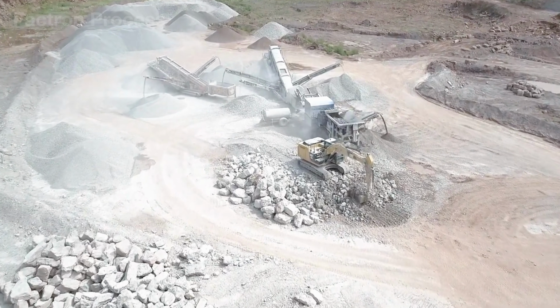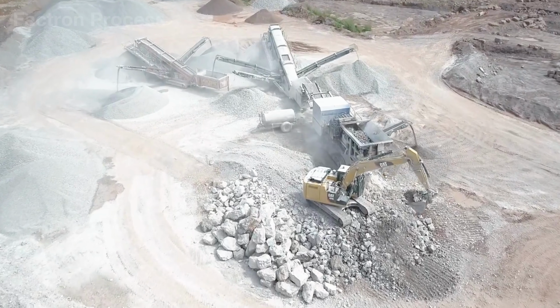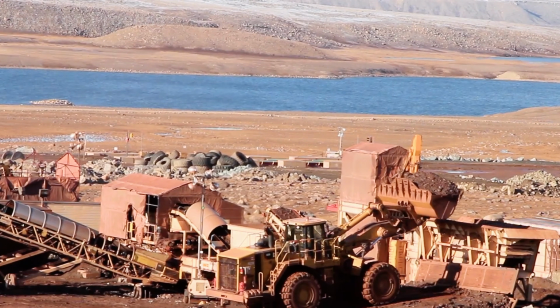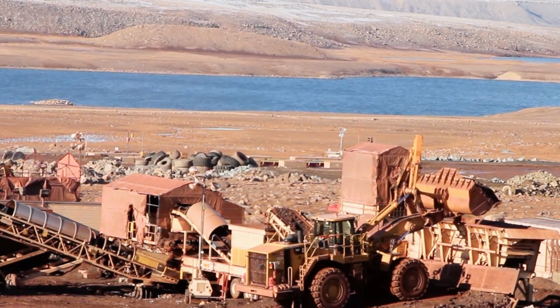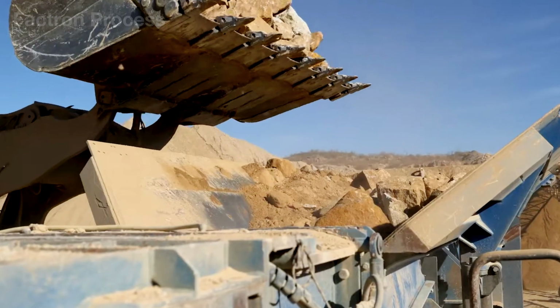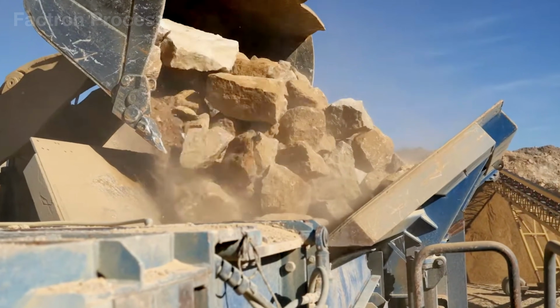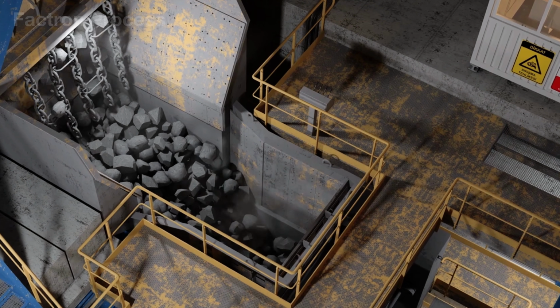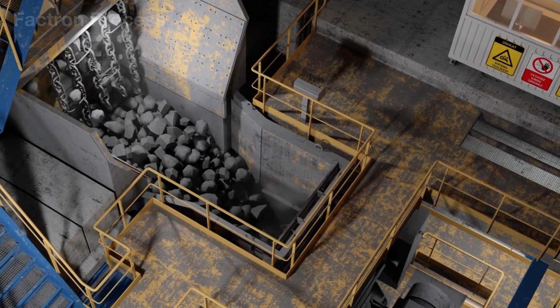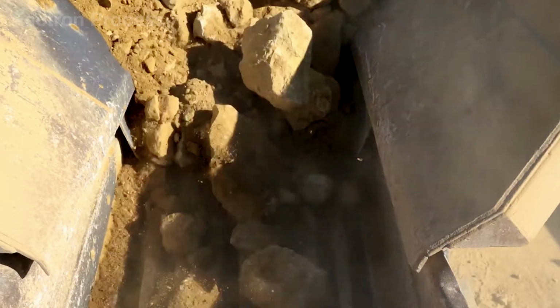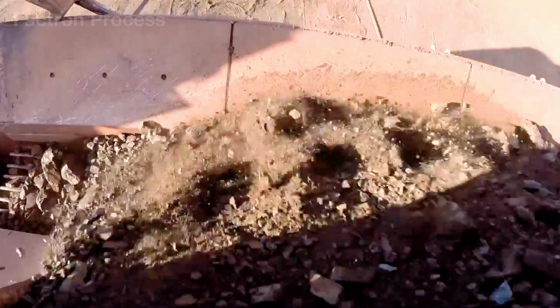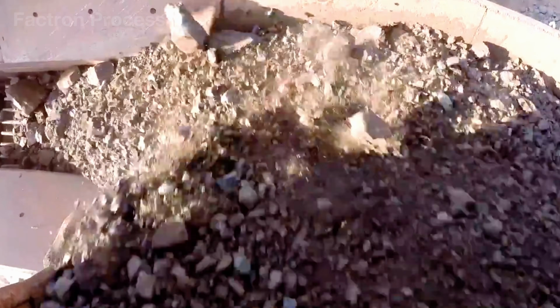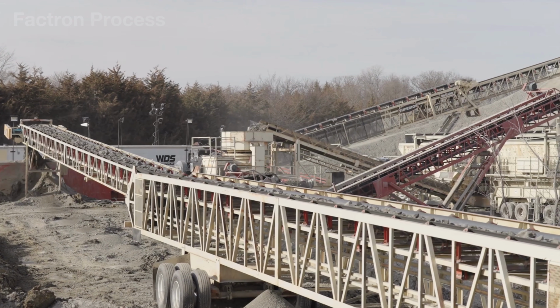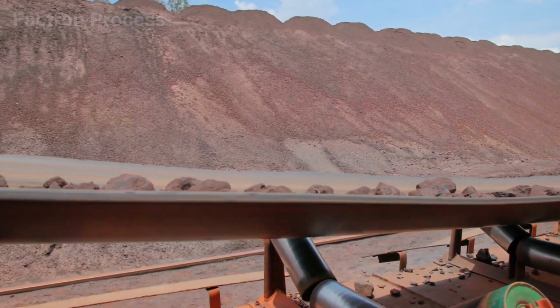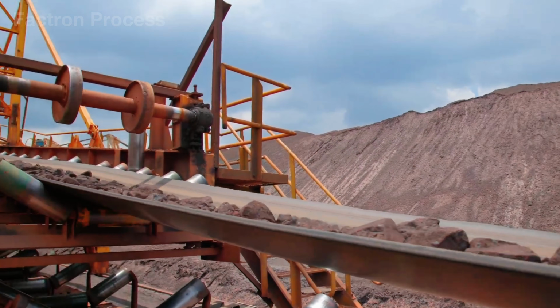Leaving the extraction site, raw rocks measuring more than 1 meter across are dumped by mining trucks directly into the feed hopper of the primary crusher. Here, manganese steel jaws driven by hundreds of kilowatts of power exert immense mechanical pressure, crushing the massive rocks down to fragments measuring between 100 and 200 millimeters. This stage releases large quantities of hazardous silica dust into the air, directly threatening workers by damaging their lungs and potentially causing chronic silicosis. Heavy-duty conveyor belts then carry the material through a secondary cone crusher.